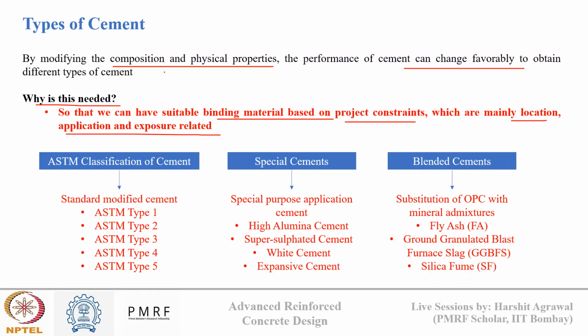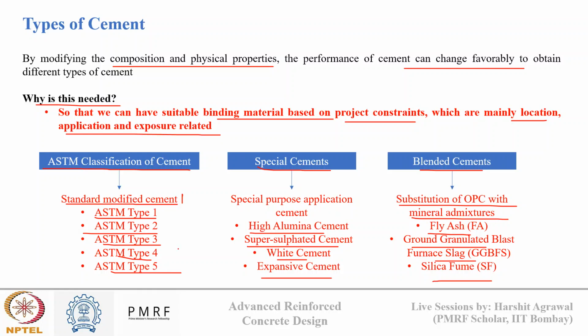This variation in composition can depend upon the proportioning of the raw meal, or on the way the cement is produced or later proportioned. There are different classifications of cement, of which I'm listing three types here. One is the ASTM classification, with standard modified cements named ASTM type 1, type 2, type 3, type 4, and type 5. We have special purpose cements like high alumina cement, super sulfated cement, white cement, and expansive cement. And there are blended cements where OPC, ordinary Portland cement, is substituted with mineral admixtures like fly ash, ground granulated blast furnace slag, and silica fume. All these cements are produced so that we can have an optimum proportioning of binding material for our application and exposure.